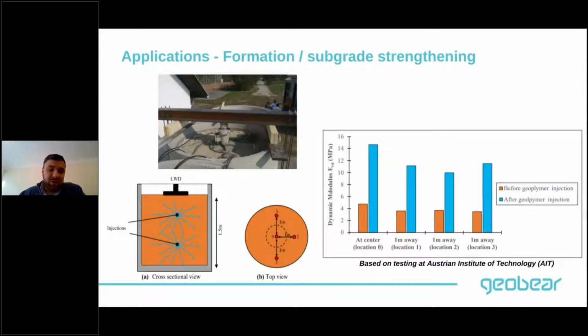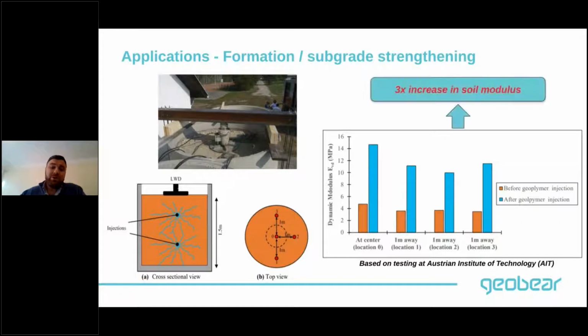But after the injections, we can see that the geopolymer managed to increase the soil modulus by almost a factor of 3. And we can even go beyond that by injecting even more material to get the design strength. So this all comes out of the design. But you can see here from this experiment that geopolymers do indeed increase the strength and modulus of cohesive soils.